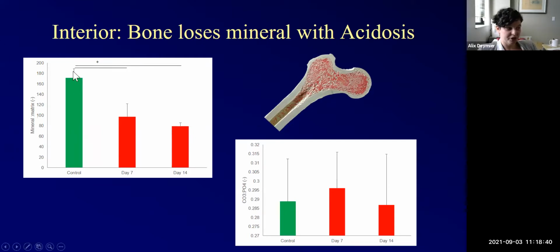Here we see that the mineral to matrix actually decreases. So now, instead of having a situation where I'm not losing a lot of mineral, I actually have significantly less mineral on the inside of my bone than I do on the outside. Carbonate, on the other hand, is unchanged. So what this points to is the fact that I must have two different mechanisms. On the outside, maybe I'm exposed to body fluids, I'm getting some sort of physiochemical response. And on the dense interior of the bone, maybe this is a cellular response where I'm getting changes in the bone turnover and it's putting in less mineral, but not changing the carbonate. At least this is going to be our hypothesis for now.